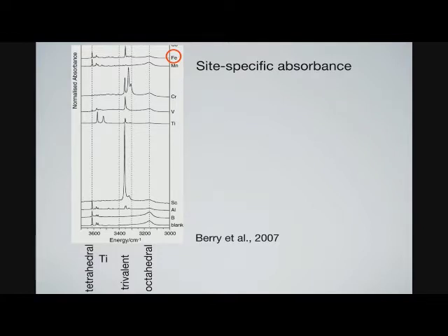The number of hydrated magnesium vacancies you get is insignificant. So there is a tension with the dry defect model: if this is really the dominant defect, for some reason either it's not there or you don't hydrate it. You can't really say which. But for hydrous olivine, it's not an important defect, whereas, by contrast, titanium is an important defect.